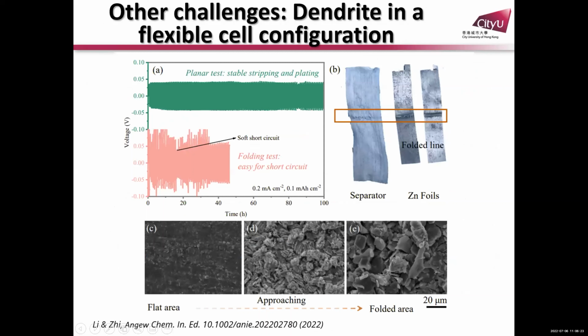On the other hand, we focused on the zinc dendrites for planar structure batteries. But if you go for flexible batteries, for example, if you fold it, then you will see that the planar cell can go, for example, 100 hours. But if you fold it, the short circuit will happen in a very short time. And if you look at the morphology from here to here, you will have large dendrites on the surface at the folding area.